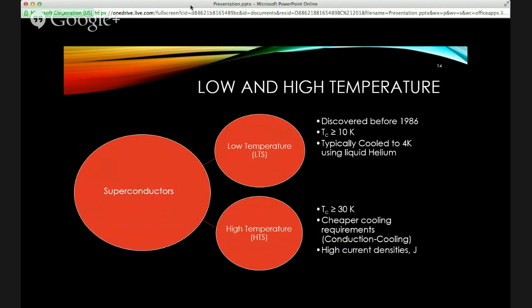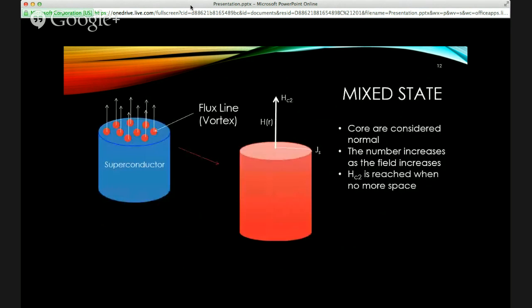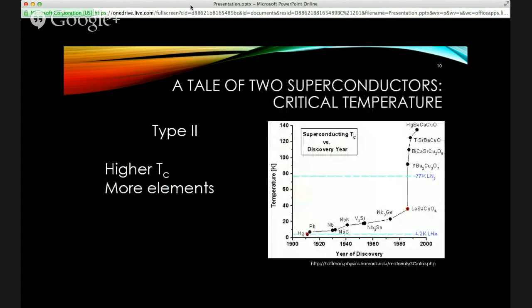They have cheaper cooling requirements because, as I mentioned, things in nature tend to want to be in equilibrium, and temperature falls into that. And they also have high current densities. So we have a spike right around 1987. What happened was, prior to that, none of the superconductors had oxides. Right around 1987, someone, actually at IBM, decided to include an oxide in the structure. And from there, we saw the critical temperature take off, allowing us to actually use liquid nitrogen.